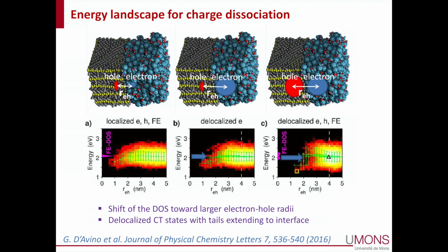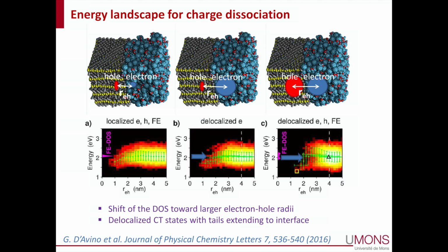And what is reported here is the CT energy as a function of distance between the electron and the hole. This should look something like a Coulomb law. And in fact, it doesn't really look like that. You see that it's something that is really flat on average, but with a large dispersion. And at short distance, you have these strongly bound pairs. So this is in a picture where the charges are completely localized.